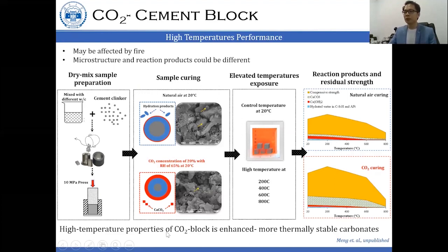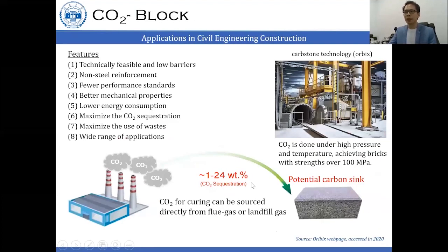So we know that the CO2 curing is beneficial for the high temperature property of cement block, at least up to 600 degrees. And for the applications, this is also technically feasible and low barrier because we can easily set up the curing chamber in the conventional cement concrete plant. And we have no concern for the steel corrosion. And also, we have fewer performance standard requirements as compared to structural material.